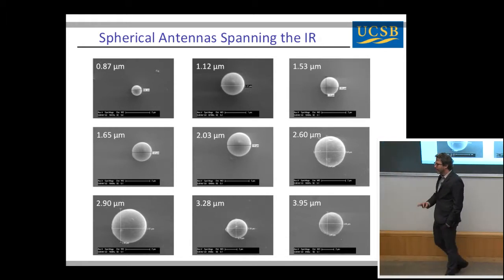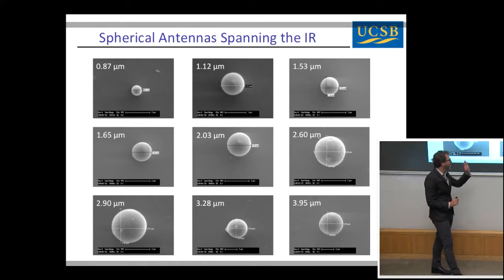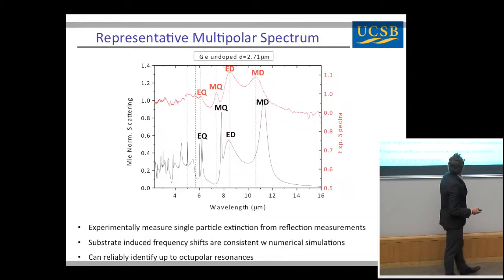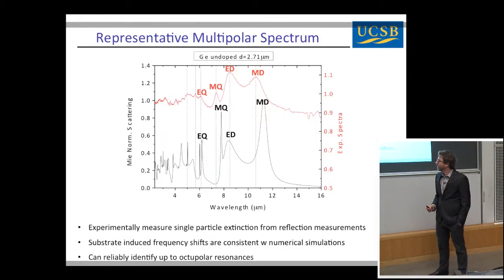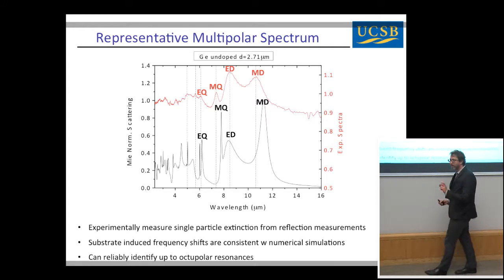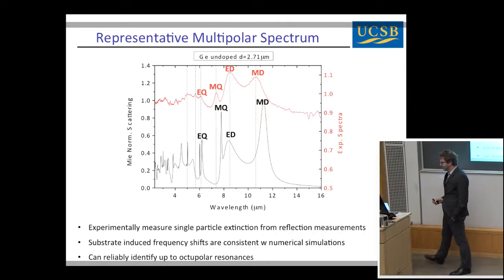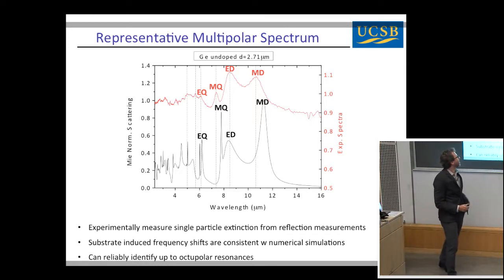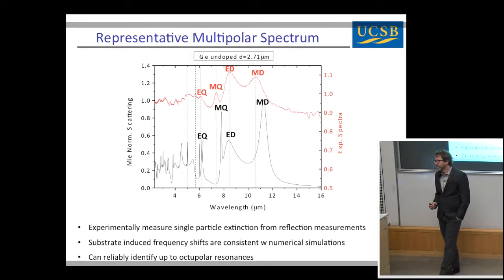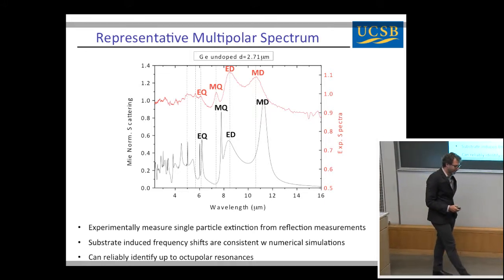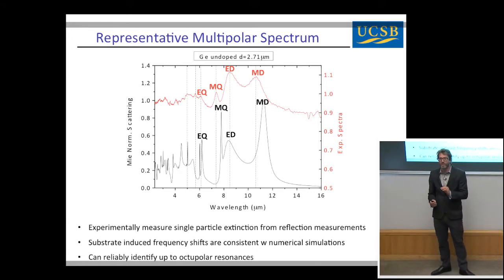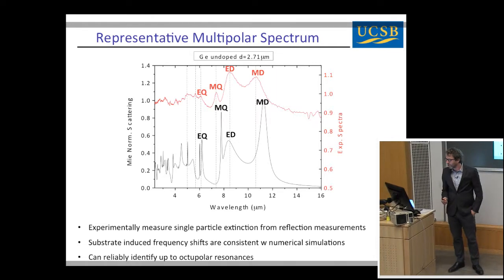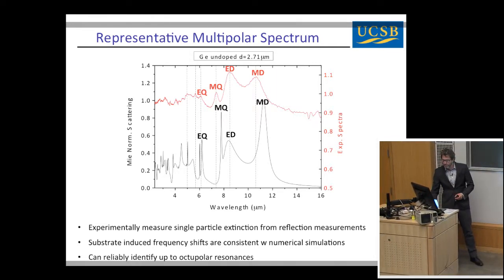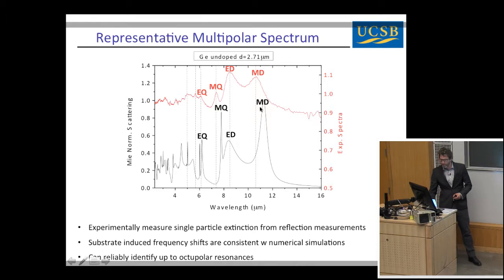Okay? So we can look at sub-bandgap wavelengths where these materials are effectively lossless, and we can look at things like this. What I'm showing up here is an experimental scattering spectrum of a single particle in red. And we're comparing it to our Mie calculations in black. Okay? So firstly, I just want to say that these kinds of measurements are not trivial. We're the first group we know of that have looked at infrared spectra of particles this small. And what you can see is that we have these multipole resonances. Here's a magnetic dipole mode in the associated theory. We can explain these shifts due to substrate effects. Here's our electric dipole modes. We can see the quadrupole.